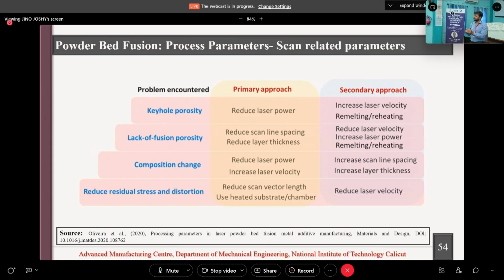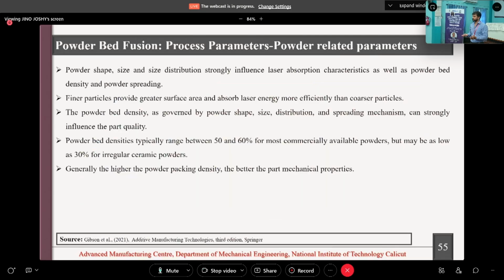Okay, so one of the strategies we are using is to reduce the scan vector length. That means the track length will be very, very small, and we use a heated substrate or chamber, which is another strategy for reducing the residual stresses.